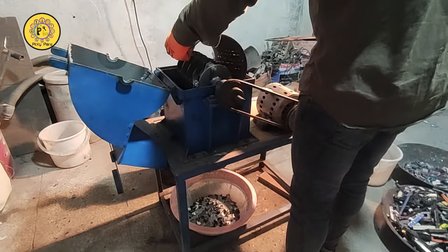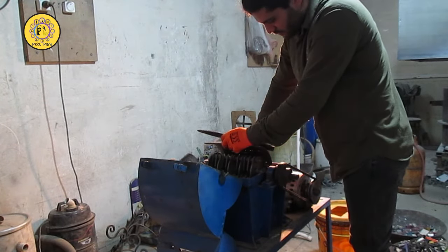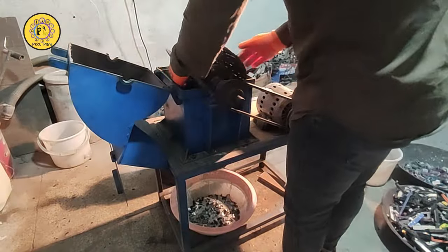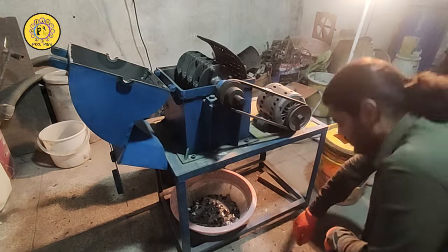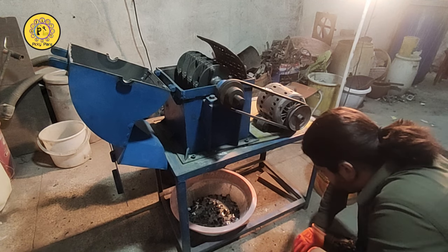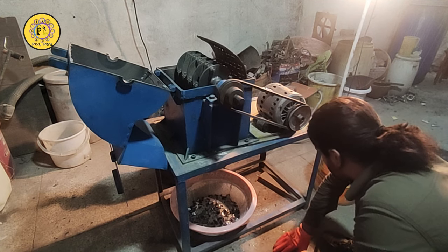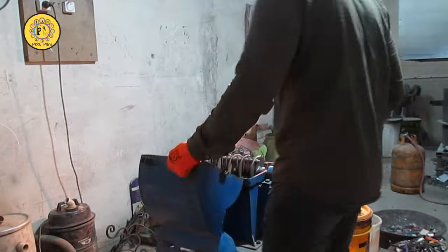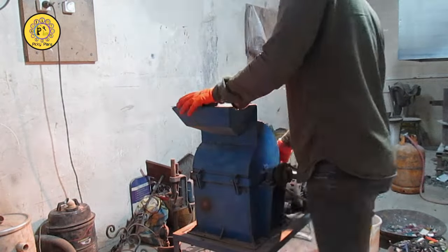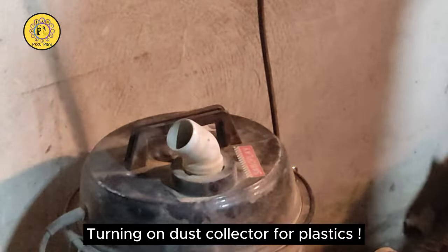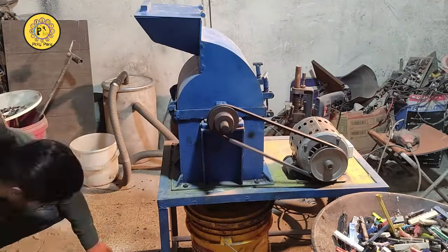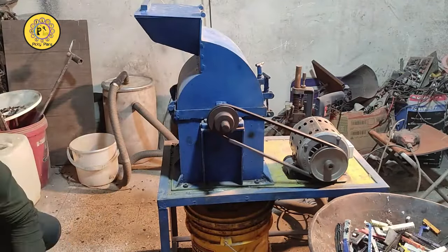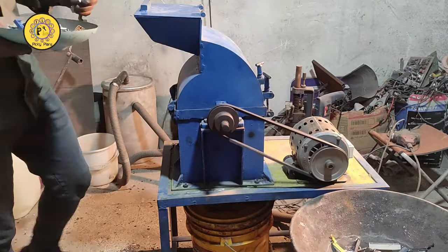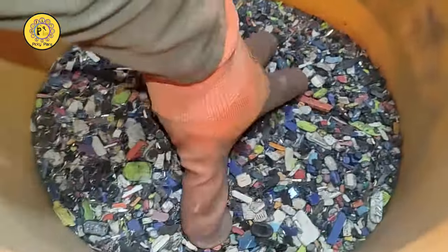This way I can separate good materials from the bad materials. Good materials would be sorted into the bucket, and bad materials, the majority of which are steel cover, would be inside the other dish. I put the screen back inside of the hammer mill, and then I continued milling the pins to get all pins separated from the plastic. Here is crushed material ready for gravity separation.